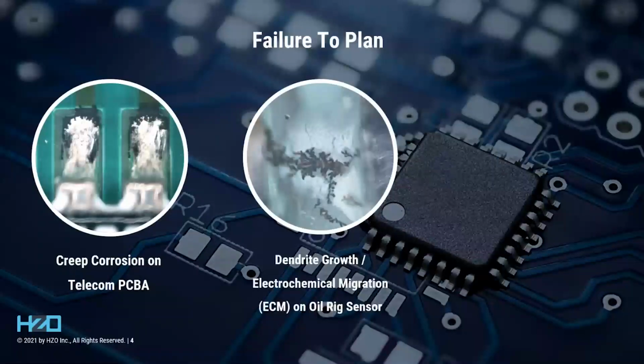This can be intermittent and latent due to the time it takes for this to fail. It can start as a high resistance short, which you might not notice because it mostly impacts just a signal, degrading the current slightly. However, over time, the density of the dendrites increases, which reduces the resistance until full failure occurs.